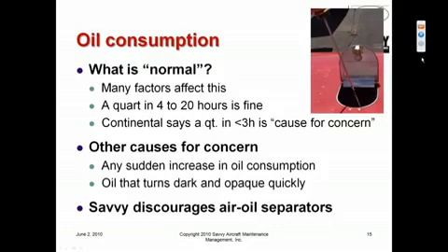Continental provides some guidance. Lycoming does not really provide any guidance that I've ever found about how much oil consumption is too much. Continental provides two pieces of guidance. In one, they say that when oil consumption gets up to about 1/3 of a quart an hour, or a quart in 3 hours, it's a cause for concern and some troubleshooting should be done. If it gets up to a quart in 1 hour, they say the engine is unairworthy.